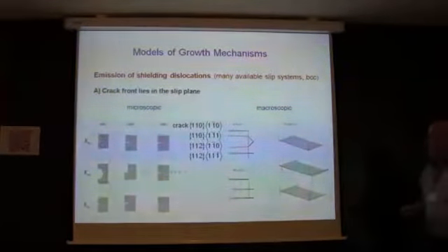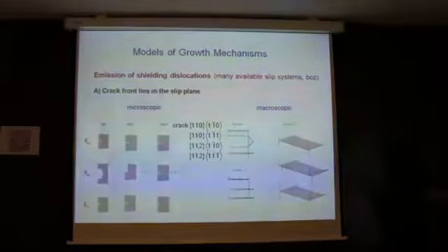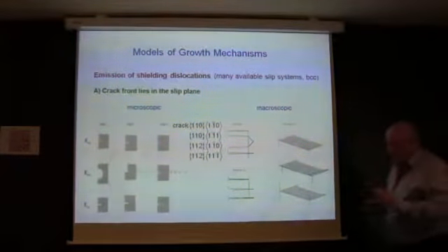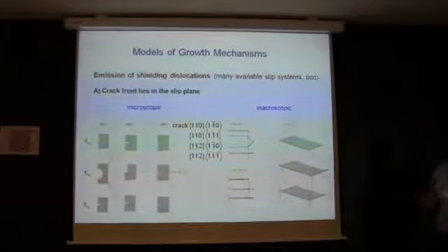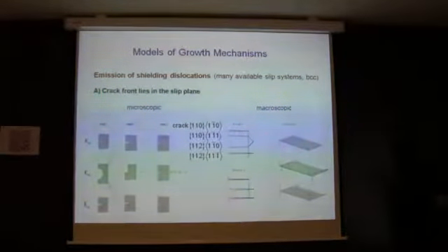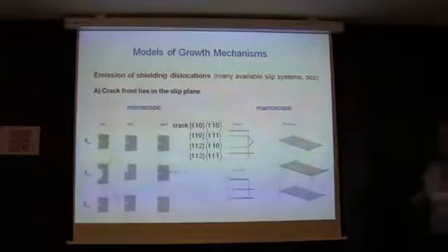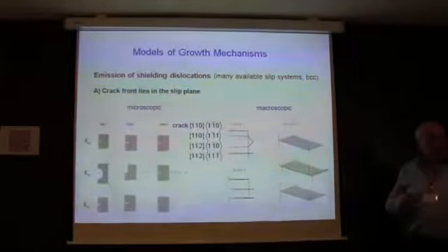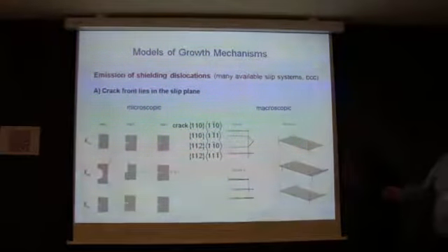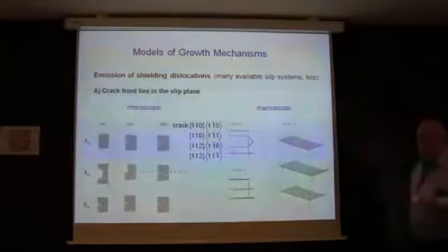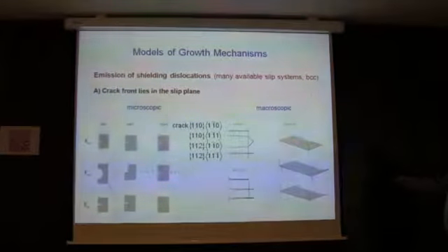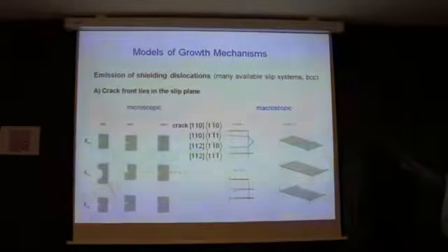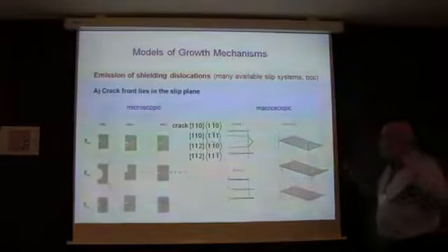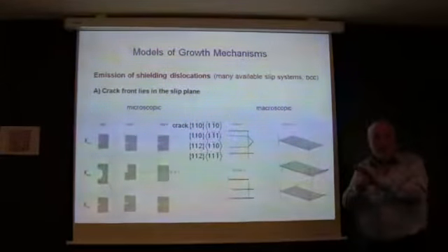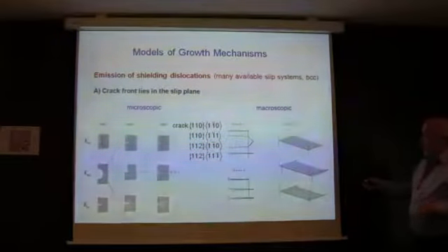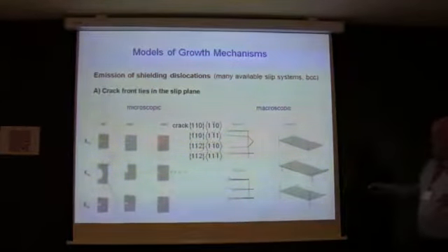Now, something about the models. Just at the moment, you have two basic micromechanistic models of crack propagation. The one is well known. It's actually emission of shielding dislocations from a crack tip, the blunting of the crack in the mode 1 case. So this works. I will mention it later on. Rather for BCC systems where you have many available slip systems with small angles in between. But the models concern very simple cases.